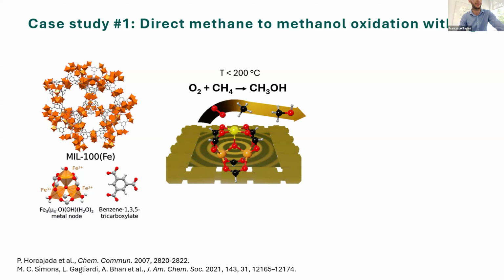In the pristine MOF, these iron sites are in the 3+ oxidation state. They are all octahedrally coordinated, and 2 water molecules cap the octahedral position for 2 of the iron sites, and the 3rd iron site here is coordinated either by a hydroxyl or a fluoride, depending on the synthesis. So we were interested here in understanding the mechanisms, the molecular factors influencing the ability of this MOF to catalyze the reaction between methane and oxygen to form methanol. This is, of course, a very relevant reaction for the chemical industry.